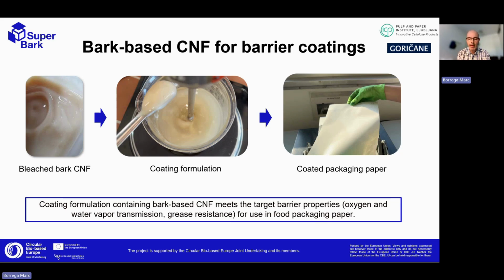This is done by taking the bark residue before doing the fibrillation into nanocellulose. So we do a bleaching process to remove some or most of the residual polyphenol. You can see that it clearly has a whiter color than the starting nanocellulose. Here we have also used the unbleached nanocellulose, but the bleached nanocellulose works the best.